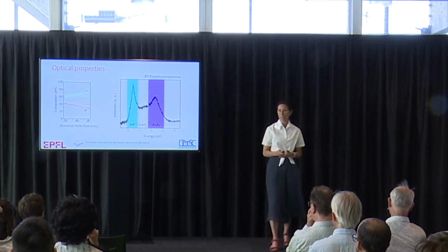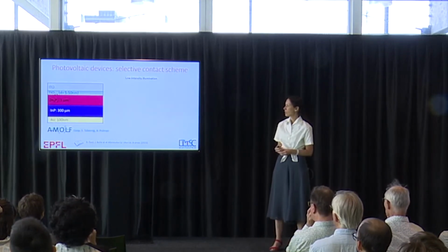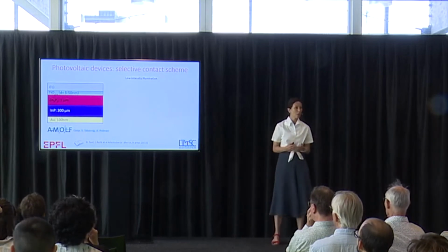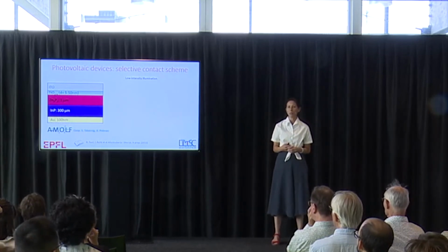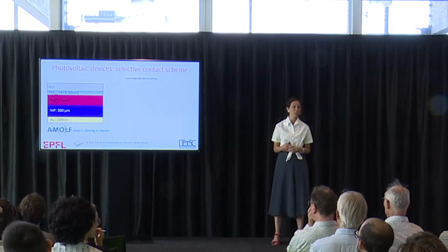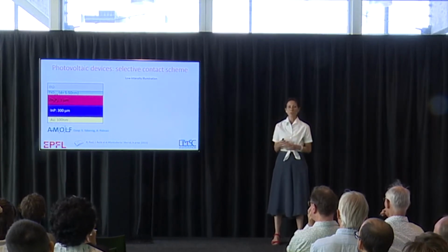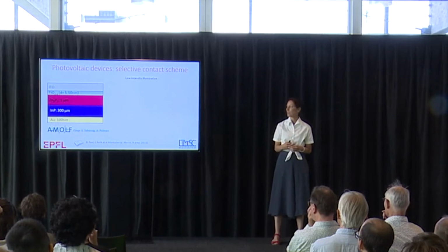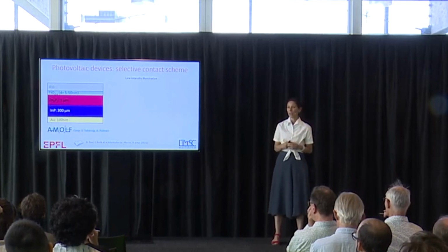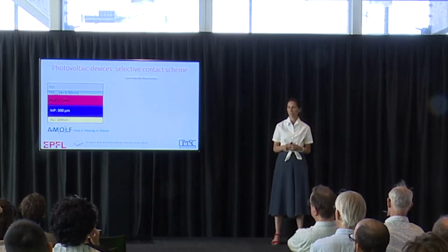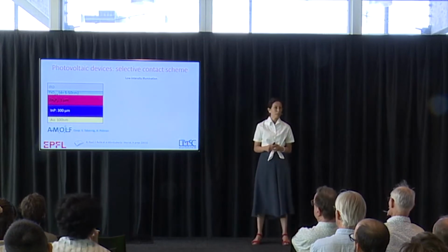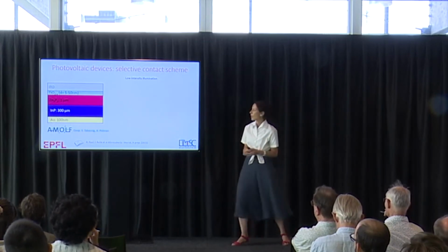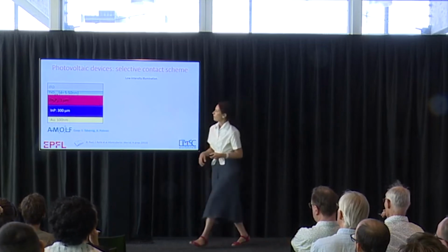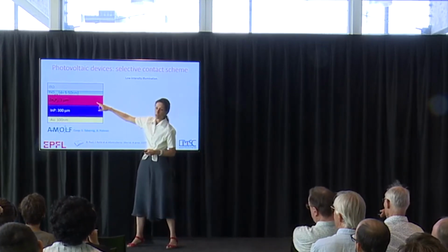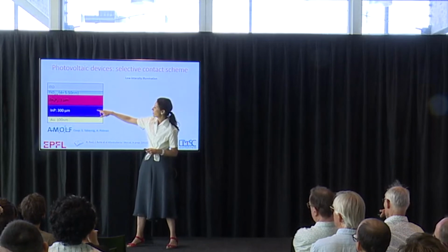And now to finish in an even more optimistic way, here are some recent results. We had the group of Albrecht coming this year, and we brainstormed on what the structure of the solar cell would be. We were too fixed on getting a PN junction; in fact, you don't need this. You can think about a structure where you only need selective contacts. Stefan did simulations, and they told us what materials we can use. So we tried zinc phosphide. Unfortunately, we still use indium phosphide as a substrate.